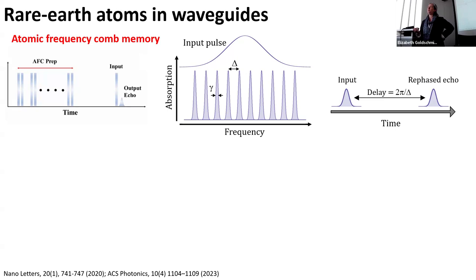It's a very good question. There are papers in the literature doing detailed calculations of the efficiency of atomic frequency comb protocols. My guess is it doesn't matter much. There are some fundamental limits to the efficiency. If all you do is this, you actually can't store more than 50-ish percent efficiency. In practice, you can't store more than a few percent. No, that's actually because of the reabsorption. There's an optimal optical depth that you hit, beyond which it gets worse. But if you put the whole thing in even a really bad cavity, that limit goes away. So yeah, there has been a fair amount of work done on the theoretical side of this, but again, all real atomic frequency combs are bad because there are so many practical limitations today.